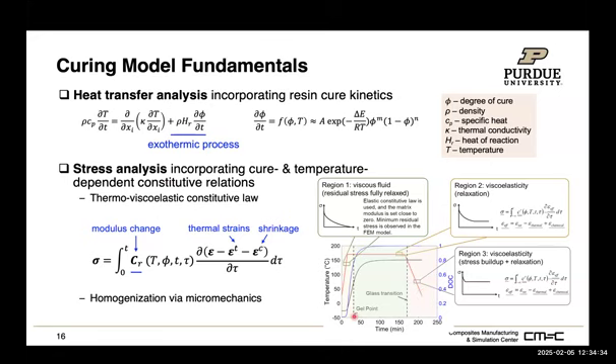When we do the infusion process, it's just like a liquid, right? So we actually have to carefully monitor the viscosity change, because when the viscosity is suddenly increased, we know it will pass the gelation point. After that, the polymer can no longer flow, right? And then it will be in a kind of rubbery stage where the polymer starts to develop cross-linking, so it starts to form stability and stiffness, but at the same time, it can also have a huge capability for stress relaxation. So we have to treat this as a viscoelastic material. And at the end of the day, when crossing the vitrification point, which is the in-situ glass transition point, it's where it develops the final stiffness of the part.